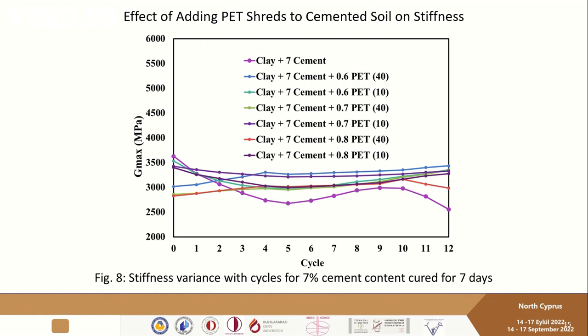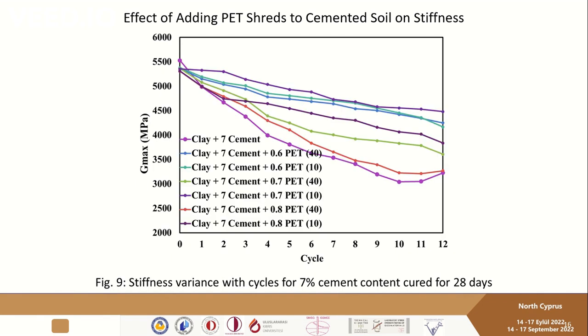Also, if we consider the effect of adding PET shreds to cemented soil on stiffness, we can see that regarding the 7 days of curing, the shear modulus in the initial cycles got reduced, and then in later cycles it got increased up to the 12th cycle. But in the case of 28 days, as you can see, it kept reducing, like the stiffness was getting reduced from the first cycle up to the 12th cycle. However, the loss of stiffness was getting improved. It was reduced by adding PET shreds, which is a good thing.